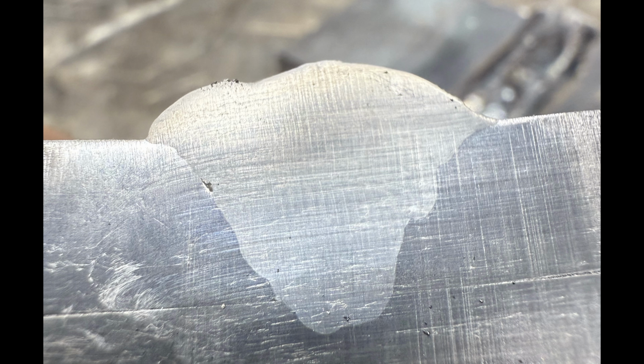And visually, you can't tell that this is going on, even in between passes. There's no indication that this exists. And that's where the biggest issue is with this. There's no way to know without actual radiographic x-ray testing that this happens. Now, as far as how weak this is, if this was on like an excavator arm or something and it was stressed, more than likely a crack will propagate right through there and your weld will fail.